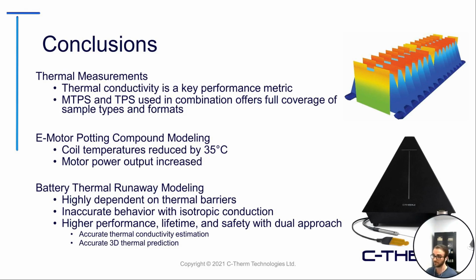And as well, again, the really important aspect of the battery thermal runaway modeling, noted to be very highly dependent on those thermal barriers. Again, highlighting that isotropic behaviors may lead to inaccurate real-world conditions. So the ability to understand the anisotropic aspect of some of these materials can be very important, especially for the simulation side of things. And again, the higher performance, lifetime, and safety noted with the dual approach: the thermal conductivity estimation, as well as the 3D prediction modeling.